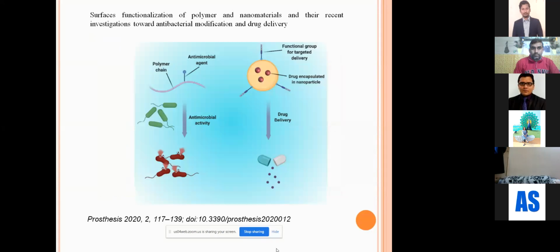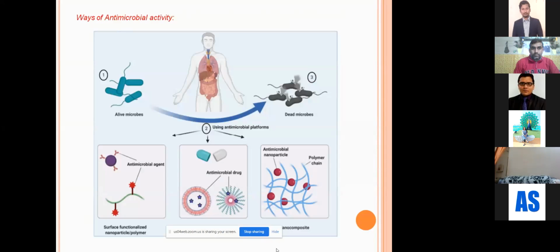So there are actually three ways of functionalization of the nanomaterial to control the antimicrobial activity. Either you are binding some functional material onto the surface of the antimicrobial agent, or you are using some fillers, for example silver nanoparticles inside the capsule system, and asking them to deliver to a particular surface where they will actually bind to the surface. They will disrupt the bacterial membrane. They will bring stress to the bacterial surface by releasing reactive oxygen species, and